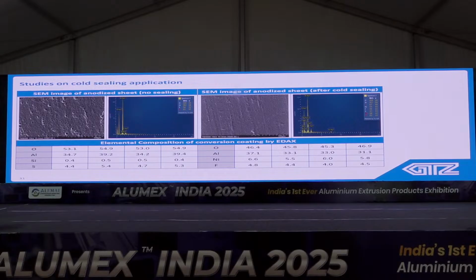Then the different SEM and EDX studies for sealing processes. First one is the anodic coating only. So aluminum and oxygen, the elemental composition of the aluminum coating, is found. We have selected four spots, and the analysis result of the four spots has been reported here. Then on the last right side is the same image and EDX analysis of elemental composition after complete sealing. Here you can find nickel and fluoride as part of the composition, coming from the cold sealing chemical.